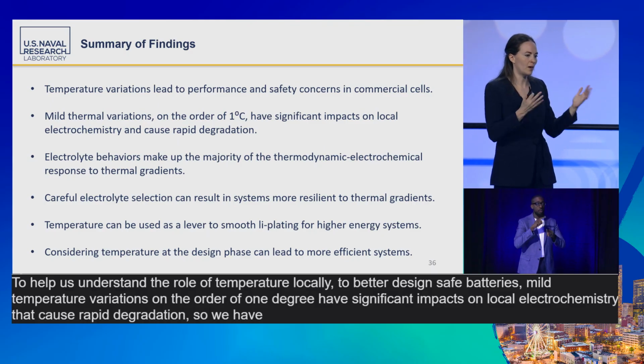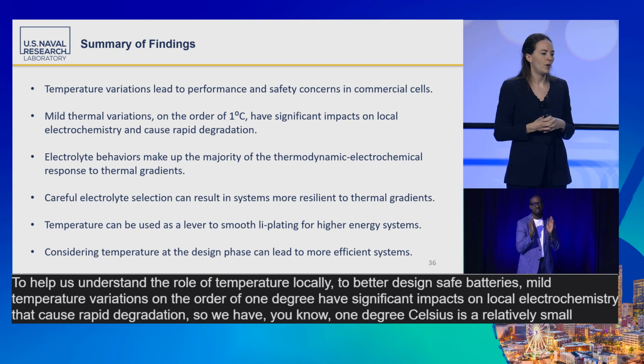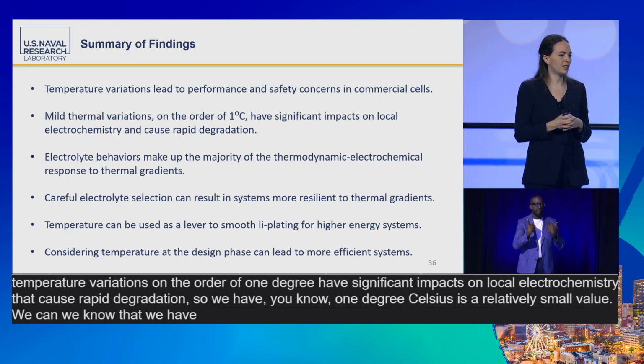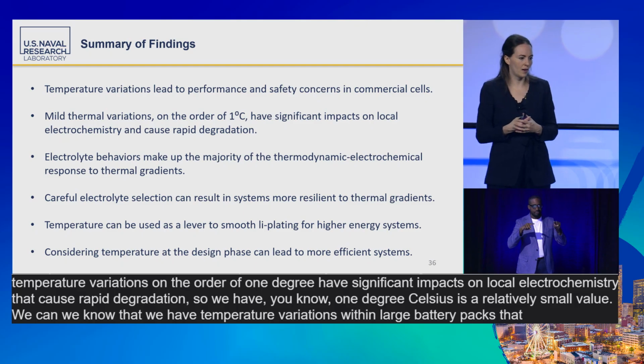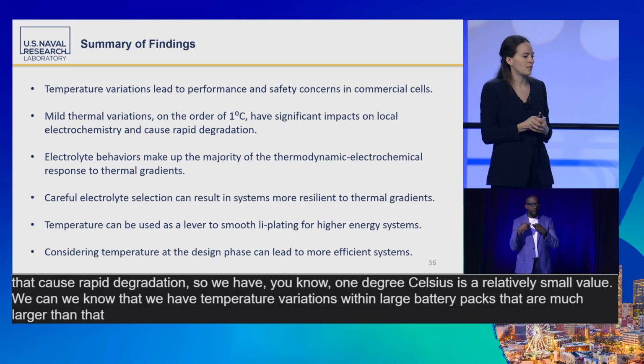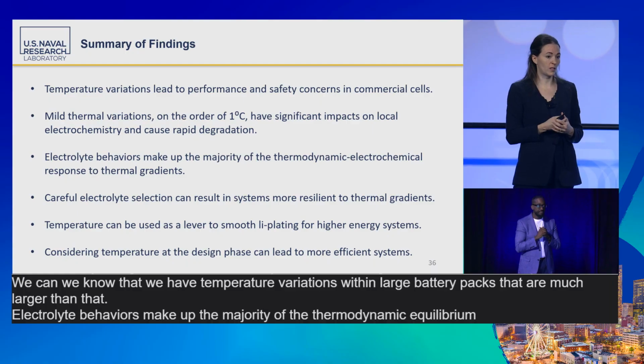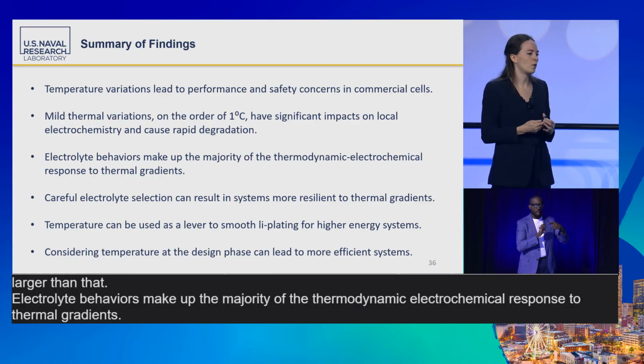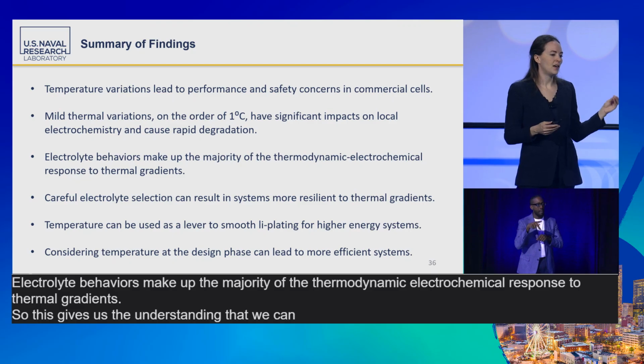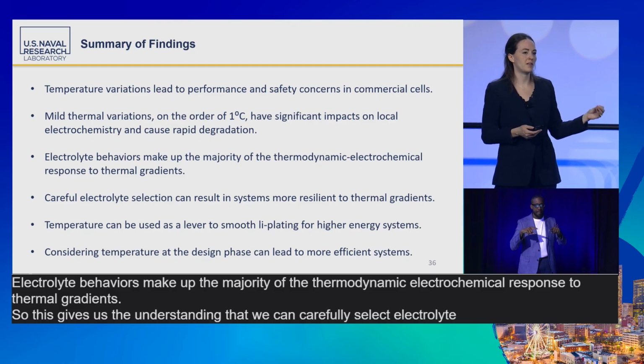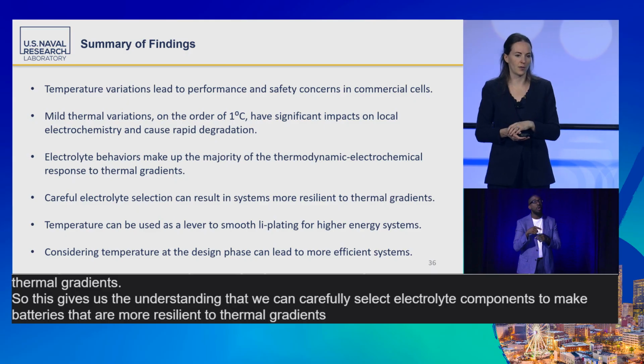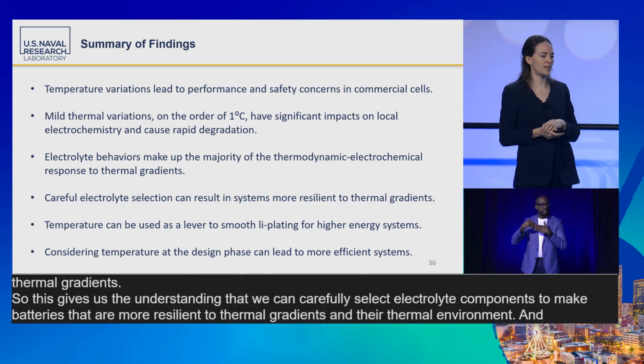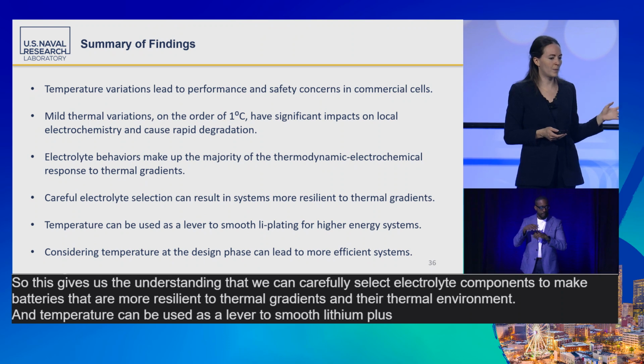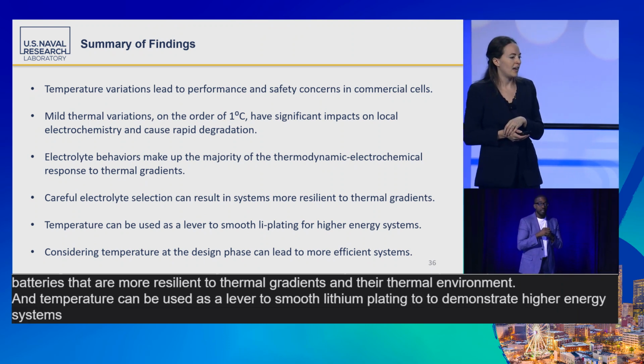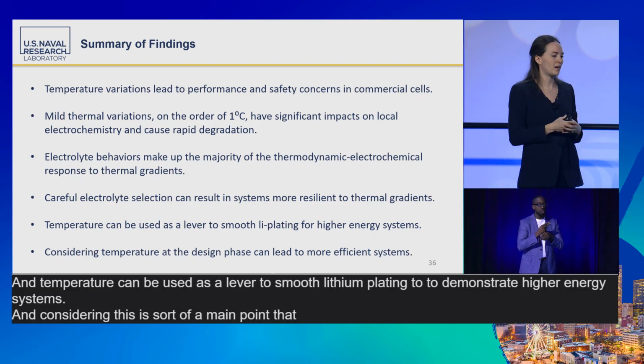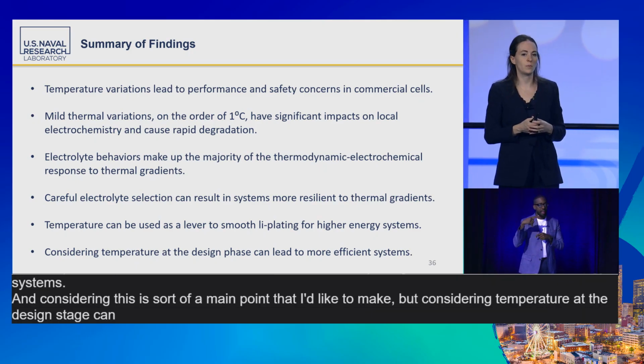So 1 degree Celsius is a relatively small value. We know that we have temperature variations within large battery packs that are much larger than that. Electrolyte behaviors make up the majority of the thermodynamic electrochemical response to thermal gradients. So this gives us the understanding that we can carefully select electrolyte components to make batteries that are more resilient to thermal gradients and their thermal environment. And temperature can be used as a lever to smooth lithium plating for higher energy systems. And this is the main point that I'd like to make: considering temperature at the design phase can help lead to more efficient systems.